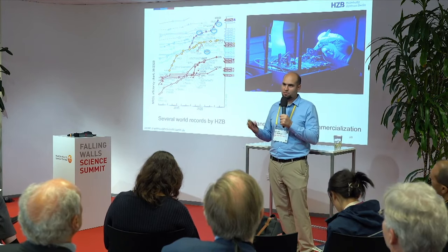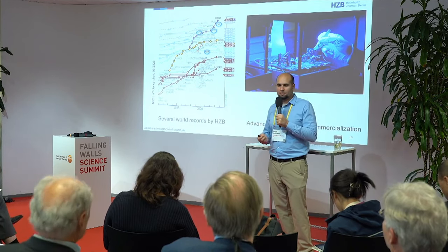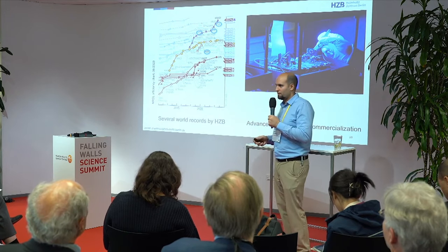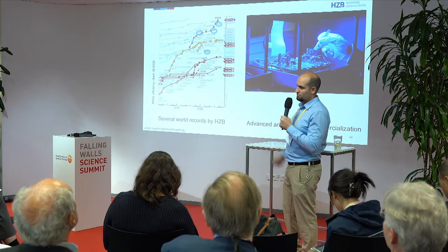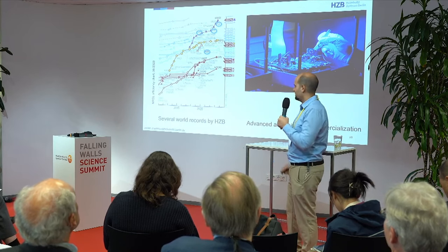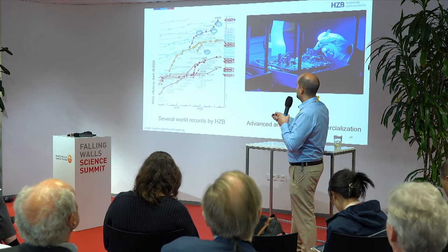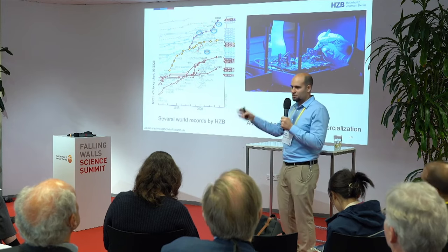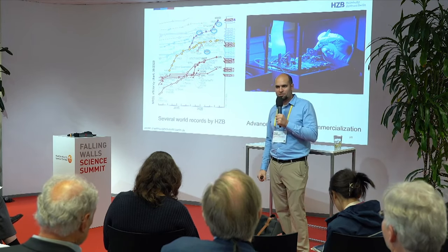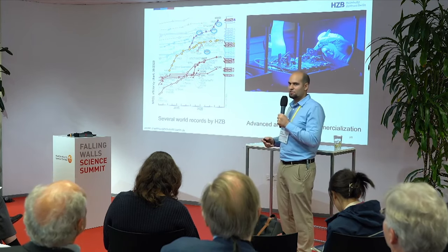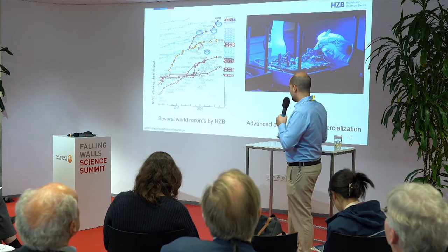So realistically, as I said, 24-25% for silicon, in the lab maybe 26 point something, but now it's easy to go over 33% with silicon perovskite. And you see the rate at which this accelerated, because of course we also took some knowledge from the organic PV community and so on. It shows how promising this material is.